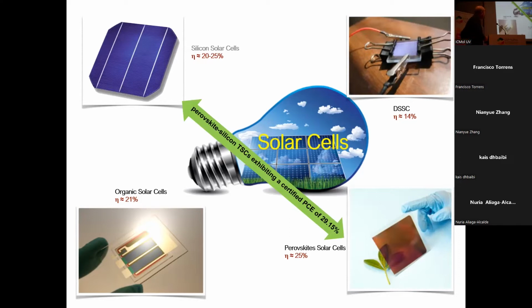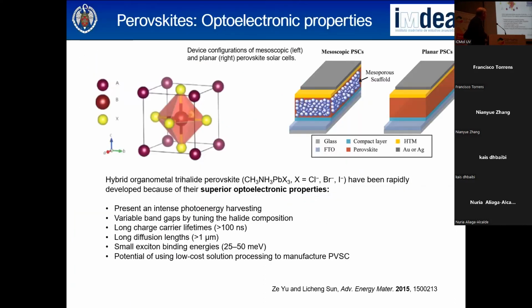But look at this: in silicon, usually the thickness of the active layer is roughly 200, 300 microns. But if you go to the perovskite, then you can find 200, 300, 400 nanometers. So we are talking about 3 orders of magnitude. The thickness is lower than for silicon. This is an important aspect to be considered. So very briefly, these are the perovskites. They have many features, significant differences with other materials.